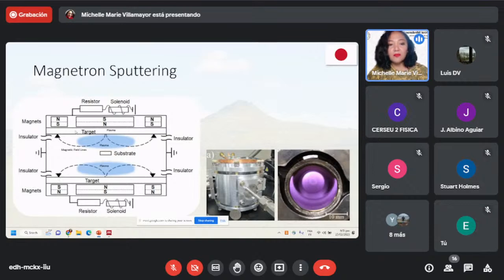So inside the chamber, we have the target. That's going to be our zinc source or zinc metal source. So we have one target on top and we have one target at the bottom. And then behind our target are magnets. And our magnets help trap the electrons, thereby increasing the chances of ionizing the argon. So we also introduce argon inside. These argon ions are the ones that are going to sputter out the target, and the sputtered out zinc gets deposited onto our substrate. Now, if we introduce water vapor, H2O, the H2 and the O get separated and the oxygen reacts with the zinc, and we are now able to deposit zinc oxide onto our substrate.